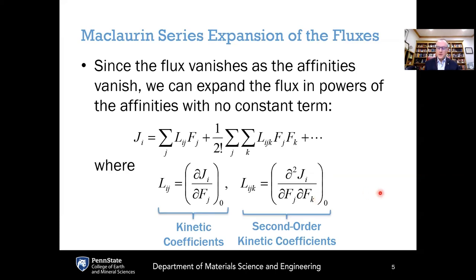Now, recall we made a few simplifying assumptions in our treatment of irreversible thermodynamics. The first simplifying assumption was that it is a purely resistive system. This means that the flux depends only on the affinities at the same instant in time, and not going back to some memory of affinities at previous points in time. With that assumption of a purely resistive system, we can write the flux of some thermodynamic variable, I, in terms of a Maclaurin series expansion where we have linear terms.